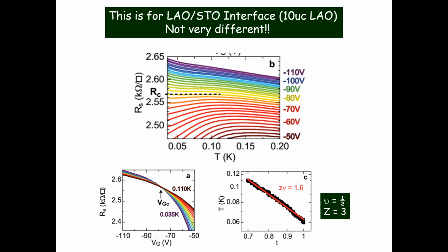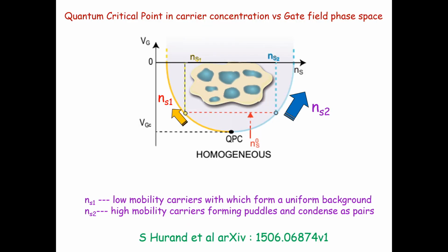And again here you can see exactly the same thing, same exponent. So this is the carrier concentration driven phase transition. And I can plot a diagram here. So it's a quantum critical point in carrier concentration versus gate field phase space. So this is my 0 gate voltage. I'm making it more and more negative on this side. And here I have all low mobility carriers, very small concentration, but they are all homogeneous. As I make my gate voltage less negative, I enter this point at which now I start seeing the phase separation. So if I go up, the low mobility carriers follow this path and the high mobility carriers follow this path. So I get a mixture where I have low mobility carriers and high mobility carriers. So a two-phase, a phase separated regime where I have superconductivity.